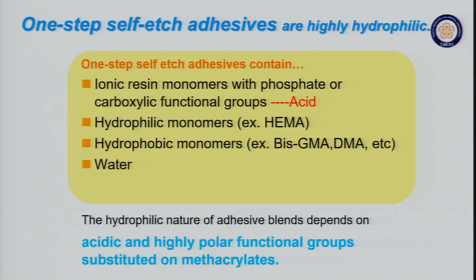And water is necessary to make this solution acidic. If there is no water, the monomer cannot be ionized. That's why we need a small amount of water. Then we need to mix the water and oil. You can imagine the dressing for salad. They are separated between the water-based and oil-based materials. That's why you have to shake it. So to mix these water and oil-based materials, we need some kind of organic solvent like acetone or ethanol.